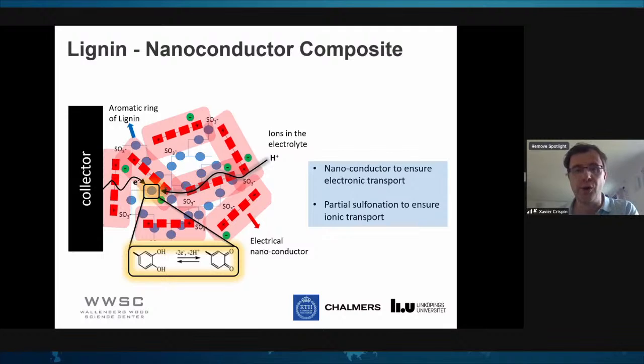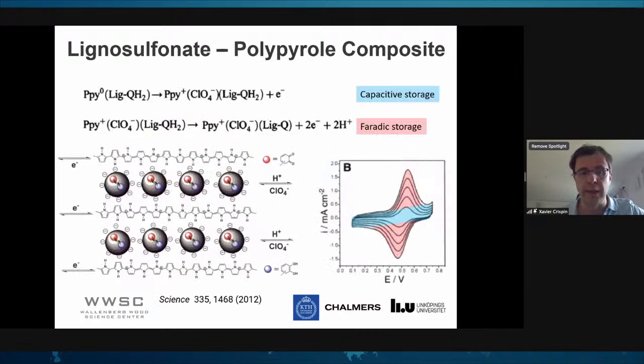So the trick is, what are we going to use? The first findings were actually made in Linköping by Inganäs in 2012, where he used conducting polymers, those molecular wires, to combine with lignosulfonate. In that case, these polymers were positively charged, and lignosulfonate was negatively charged. So you form a composite during the polymerization synthesis of polypyrrole. In the presence of lignosulfonate, you spontaneously form a nanocomposite of very interesting properties.